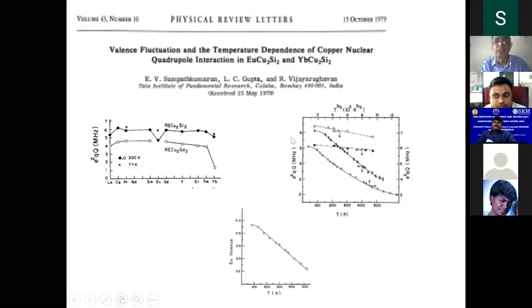And then as a function of temperature, forget about these figures, you can see a very huge change in the electric field gradient. If it is stable valent, this is what you should get: almost constant value, with very small temperature dependence because of a lattice effect. Here there is a huge variation, and you can derive the valency value from here in principle. As an approximate value, you can see the europium valency is going from almost 3+ at low temperature to almost 2+ at high temperatures.